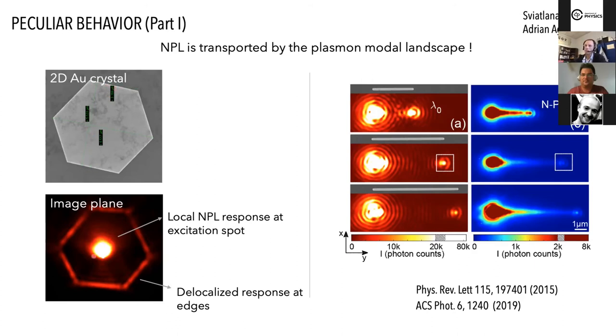And when you shoot your laser right at the center, of course, you have a strong response from the structure right at the center. This is NPL, but you can see also, and this is an image plane image, not a confocal, this is what you would see if you put your eyes in your microscope, okay? And you can see that also all the edges here are lighting up. So NPL is not only coming from the excitation spot, but is also coming from the edges of the structures. Okay. And this was very surprising to us.